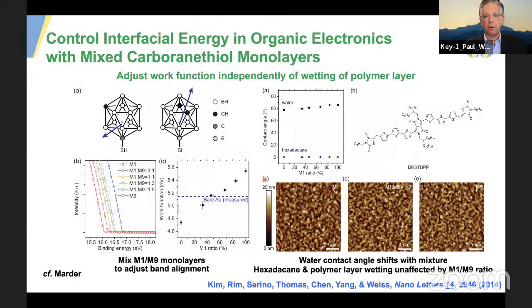And a postdoc in my laboratory, Jay Kim, figured out that he could use this for band alignment for organic electronics, where the idea is that in the active layer, you want to match the contact, which in our case here we've measured both gold and silver. And people like Seth Marder at Georgia Tech use a polymer interlayer that they fluorinate in order to add negative charge in order to shift the bands. But that has the property of making the interlayer more like Teflon, and so one changes the wetting properties.